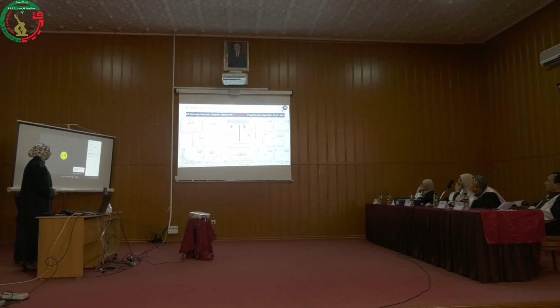On the right side, we have illustrated the relaxation times that show the same variation for all the compounds, since it decreases with increasing concentration. And interestingly, the relaxation time for holes is 10 times higher than that of electrons. On the left side, since our p-type values show good results compared to their n-type, we have only illustrated the p-types, and interestingly, the figure of merit shows enhanced values reaching 3.5 for all the codoped compounds, indicating the applicability of our compounds in thermoelectric applications at high temperatures.